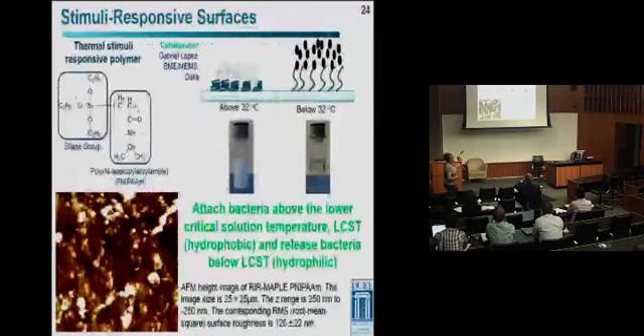Another type of polymer that's interesting are stimuli-responsive polymers. So you have some type of external stimulus and you can change the conformation of the polymer. In this case, we looked at PNIPAM, which becomes soluble or non-soluble depending on its temperature. Above 32 degrees, you can attach bacteria, and below 32 degrees Celsius, you can release bacteria. We have a silane group here so that we could have it attached to our surface during deposition. So we deposited these by MAPLE.